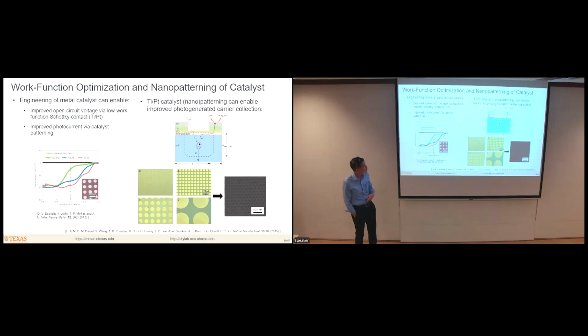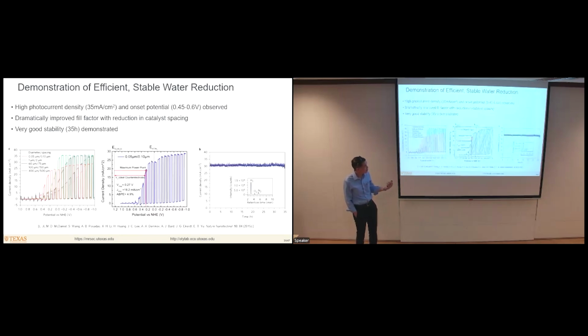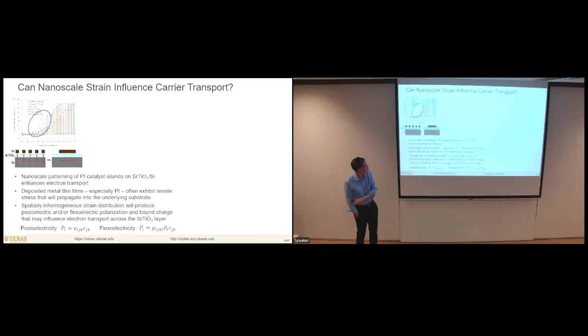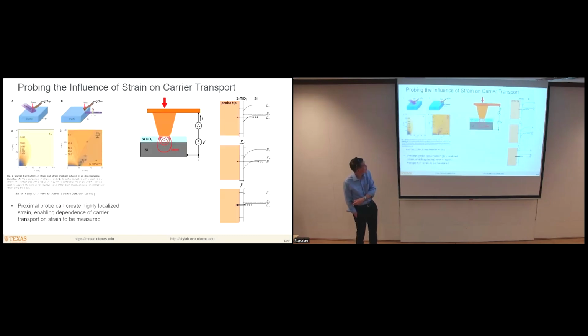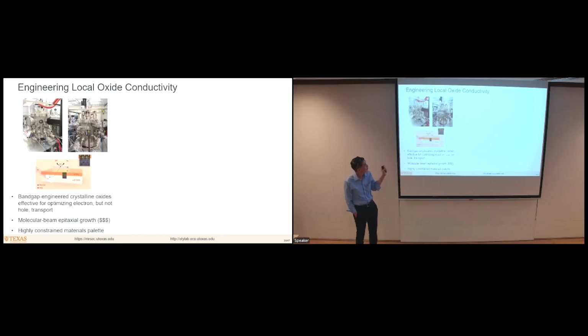All right, and what we saw was that when you went to this very small size scale, you actually got much better performance in the photoelectrodes. And so we were able to show that using these approaches, you could get very good performance on an absolute scale and very good stability as well. All right, I will skip what we've done to explore why that is the case, and instead sort of move on to where this might lead to. All right, so once we demonstrated this, we started thinking about, okay, are there ways to generalize this approach? All right, but that turns out to be quite hard, right?